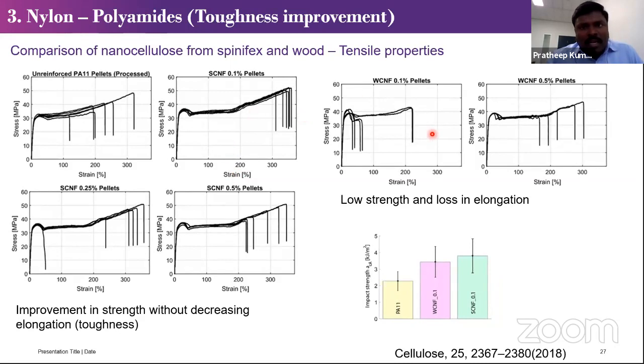When you add another type of nanocellulose, something like wood nanofiber, you can see that it doesn't increase the properties, and it actually decreases the elongation. So you are losing the flexibility and the elongation of your nylon. Nylon is mostly used in textile materials, okay? So we need stronger and tougher textile material, okay? So this is another example.